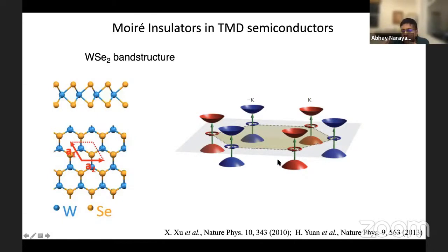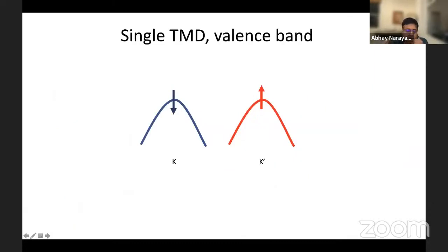And all of the physics that we are interested in is happening in the valence band of these materials. At low energy, you can essentially think about this as having 2 valence bands, one at K and K prime. The meaning of these colors is to tell you about the spin direction in each of these valleys. Due to strong spin orbit coupling, you have only one spin projection in each of these valleys. So you can think of the blue color as spin up electrons and red color as spin down electrons, if you wish. In terms of band structure, this is actually simpler even than twisted bilayer graphene, which has both spin up and spin down electrons in each of the valleys. Here you have only one spin projection per valley.